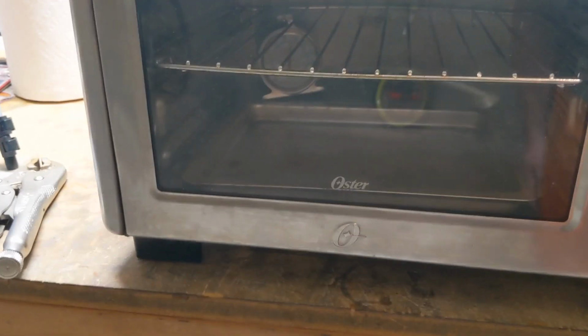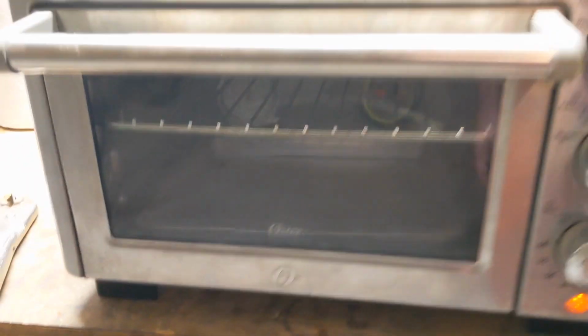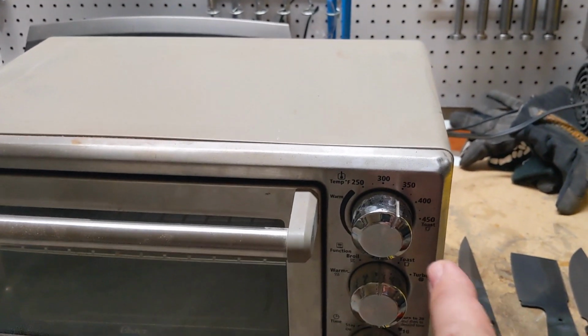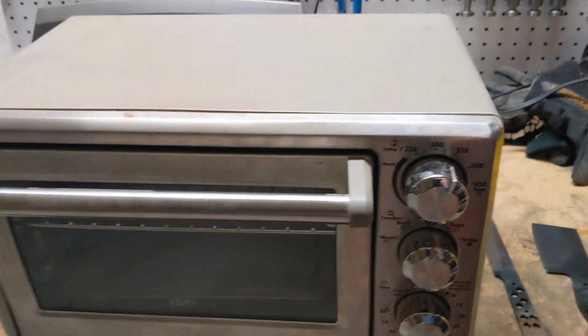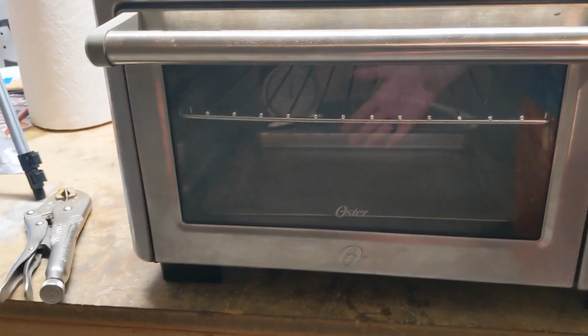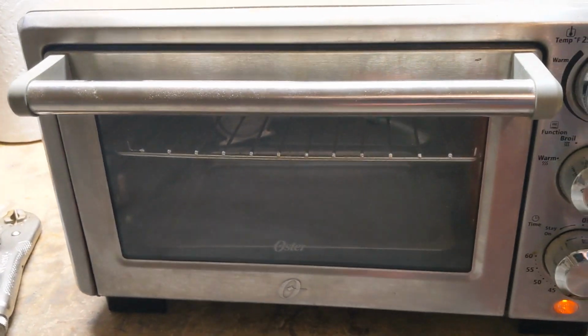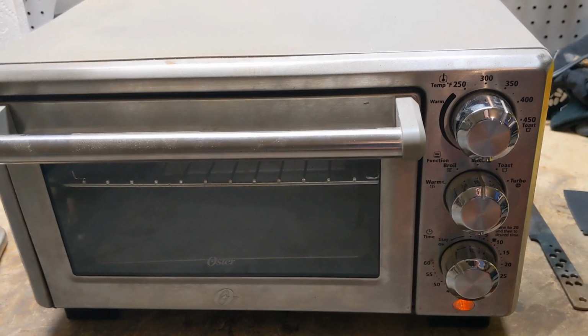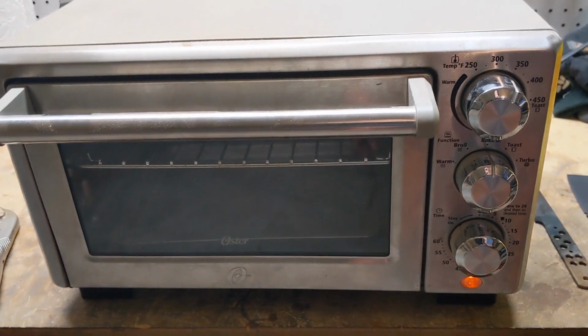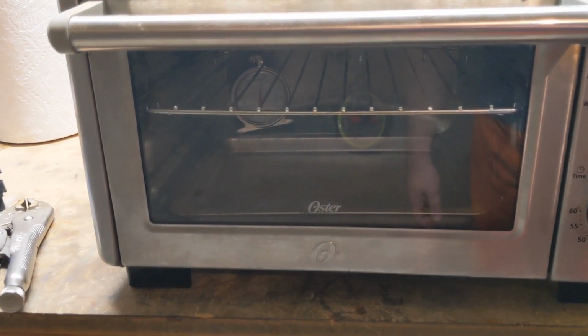If you're using a toaster oven for tempering, it works fine, but make sure you have an actual oven thermometer in there because these are not accurate at all. I have this set at 350 degrees and we're holding it at 400, which is the temperature I want. If I had the oven set to 400 degrees, it would be about 450, and the knives would just not end up nearly as hard as we want them.